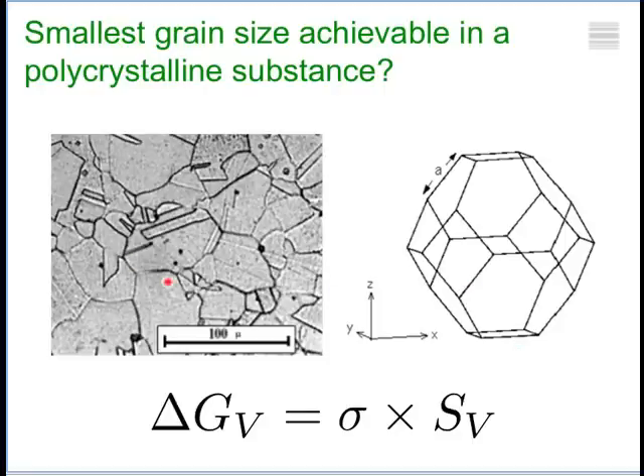Now, what is the problem in producing small grain sizes? Well, you introduce grain boundaries. Okay? These are the grain boundaries. And those boundaries have a certain energy per unit area, which we call sigma here, because they are defects. They are not perfect regions where atoms are arranged. And we also have a certain crystal size here, which tells us how much surface we introduce inside our material in three dimensions, surface per unit volume. So if I take the energy of a grain boundary per unit area and multiply by how much grain surface we have per unit volume, then this is the cost that you have to pay to create small crystals. Okay? The finer you make the crystals, the greater the amount of surface and the greater the cost of creating those small crystals. So as you go to finer and finer crystals, you will have a bigger and bigger cost to pay for getting that grain size.